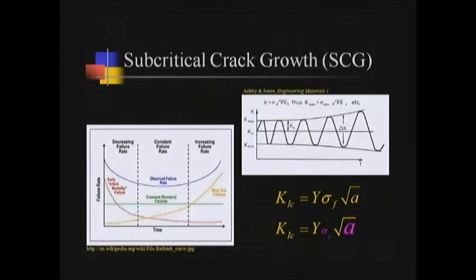And what we observe clinically is what statisticians call the bathtub distribution. If we look at how many of the restorations are failing on the y-axis, and this is over some period of time after placing the restoration on the x-axis, then we see that in red here, these are the restorations that are poorly designed, or they are placed with the wrong choice of materials for that location, or they're placed in a patient who has parafunction, and we have failure almost immediately. And those begin to fail, then the number of restorations failing decreases over time.